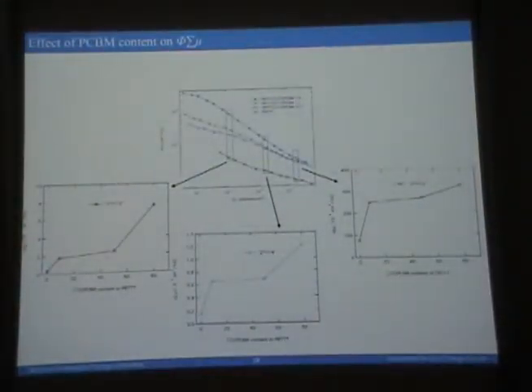So what actually happens there is you put in PCBM and it intercalates. So all you get is a signal that goes up a little bit. And you add more PCBM and that also intercalates. So the signal goes up a little bit more. At some point you saturate the number of PCBMs that can intercalate and it starts to cluster. All of a sudden the signal jumps up because you're now seeing the electrons. And so if you have a mole ratio less than 60%, you won't get a good device because you don't have clustered PCBM, whether it's C60 or C70. Go over that point, it jumps up.